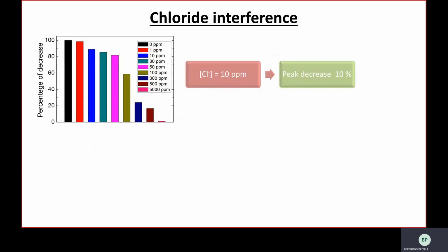Unfortunately, the presence of chloride produces a higher interference even at quite low concentration. 10 ppm of chloride indeed produces a signal decrease of about 10%. This result makes the analysis of many real water samples much harder. Drinking water has a chloride concentration of about 5 ppm, and so its analysis can still be carried out, while natural water samples have a much higher content of chloride, even higher than 500 ppm. For these samples, a pretreatment is mandatory.